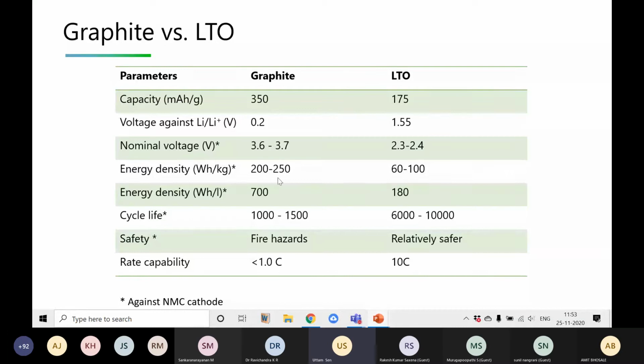And hence the energy density is also less. In case of graphite, the energy density, if you use NMC cell, then again it will be like 200 to 250 watt-hour per kg. In case of LTO, the energy density started from 60 and it can hit at max 100, but mostly it is in the range of 80 to 90.